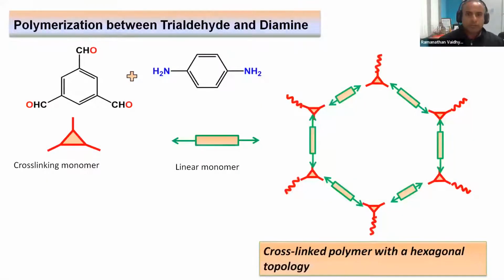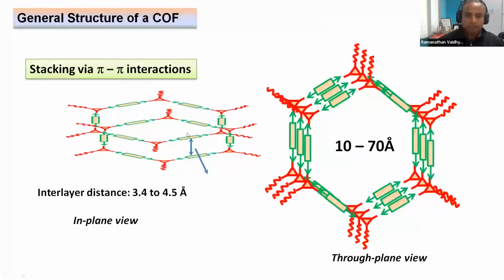For us, we look at the COF from a very simple design principle, where a COF is a cross-linking monomer connected by a linear linker, giving rise to a very ordered structure. Because of the pi stacking capability of these building units, you end up getting beautiful graphite-like polymeric structures, and the pore size and shape can be tuned by the choice of linkers or monomers, as you would like to call them. This is a very simple structure, and it gives you a chance for a wide range of functional tuning. This is what really attracts us.